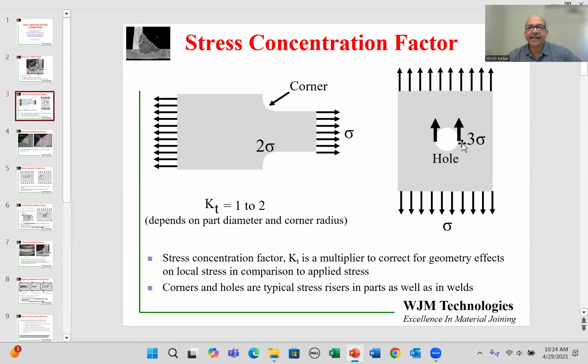If we have a plate with a hole in it and we apply a certain stress of sigma, then the stress at the edges of the hole is going to be 3 sigma, so 3 times the applied stress. So this is a multiplier effect purely based on geometry. And we can have corners, or effectively something like a corner, on fillet welds. We can also have porosities, effectively a hole in the fillet weld. And we will have stress concentration effects, which will locally increase the applied stress and which can cause some yielding.